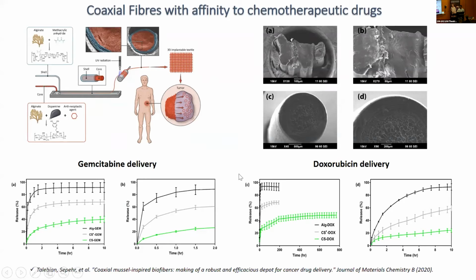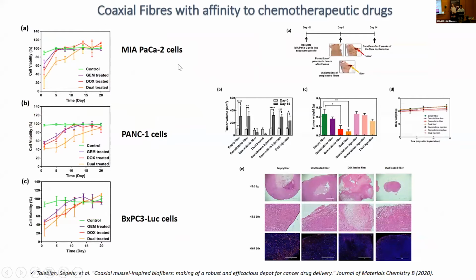So these results were promising, and what we've done was in vitro studies on different pancreatic cancer cell lines. We either had gemcitabine in the fibers, or we had doxorubicin, or we also made fibers which included both of them simultaneously, calling them dual loading. So what we observed was that when we used the dual loaded fibers, we got the best therapeutic efficacy in inhibiting the proliferation of these cancer cells in vitro over a period of 21 days.